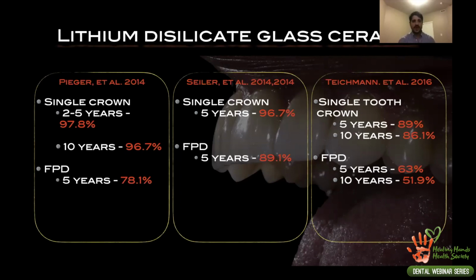When we go for FPDs or fixed partial dentures, the success rate decreases dramatically. And you have to understand the indications of the material. Lithium disilicate, according to the manufacturer, is not supposed to be used in the posterior region of the mandible and the maxilla. The mechanical properties of the material do not allow you to do that, even though we do use it in some situations. But the manufacturer does not recommend you to do that.